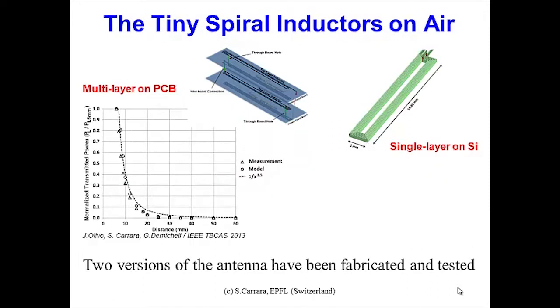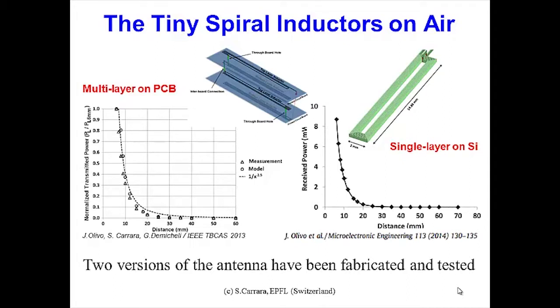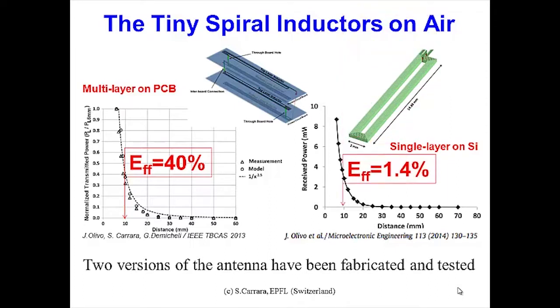We made measurements in air at different distances between the transmitting coil and the receiving one, and we repeated the experiment with quite good success, both with the multi-layer copper version and with the single layer on silicon. But the great difference is that, as expected, in the first case, for 1 centimeter distance between the transmitting and receiving coil, we reached an efficiency of the link up to 40%, which is really extremely good, while in the second case the efficiency was only 1.4%. So the first is for sure the better solution.